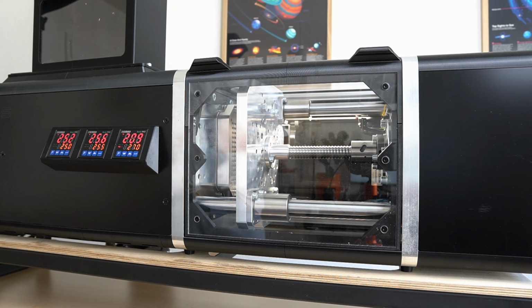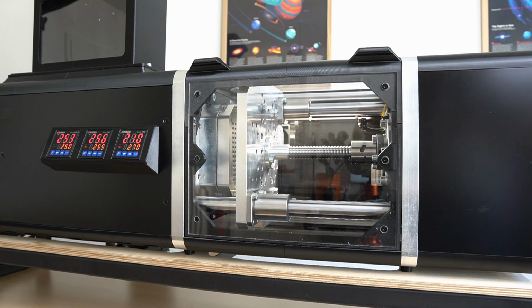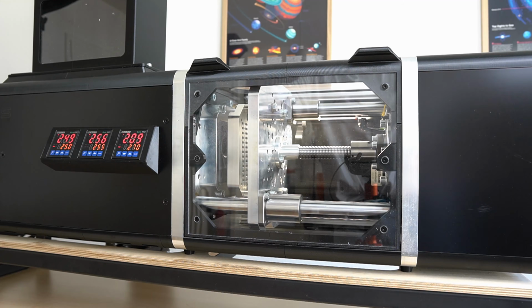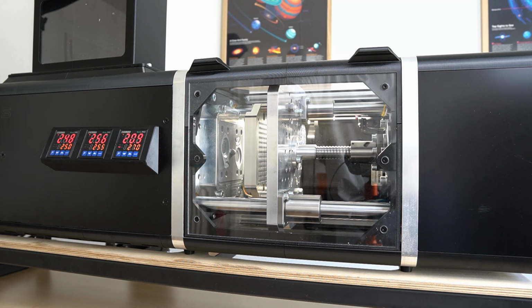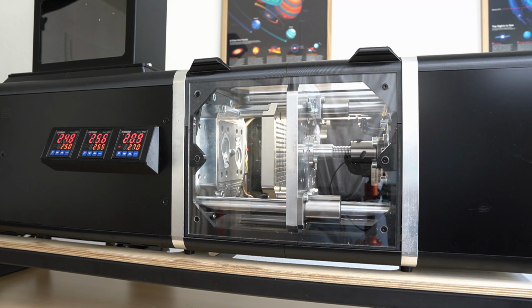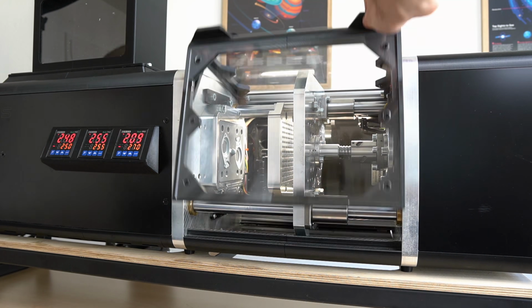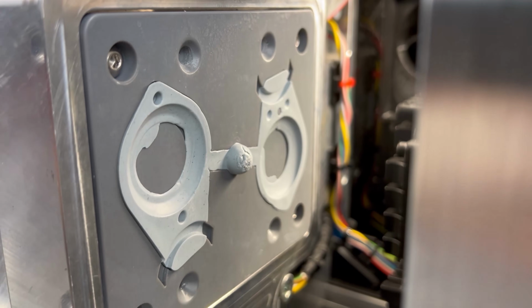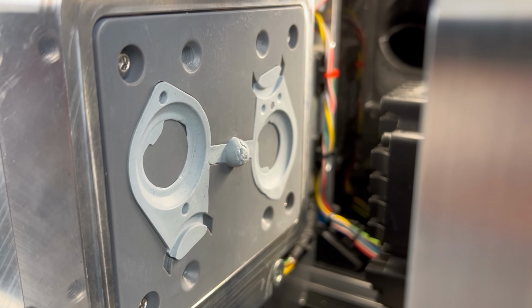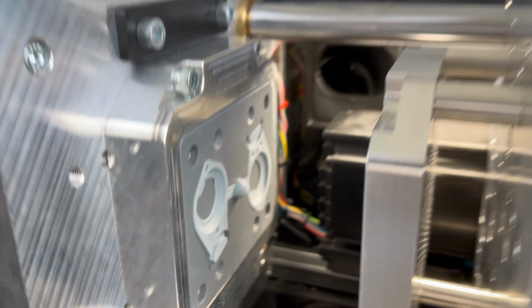One full cycle of making a keychain takes around 120 seconds, and for injection molding that is very long, and most of the time is due to the long cooldown period. Resin conducts heat much worse than aluminum, so the part takes longer to cool down. If I were to open the mold too quickly, it could still be more liquid than solid, and that is another thing to consider when working with resin molds.